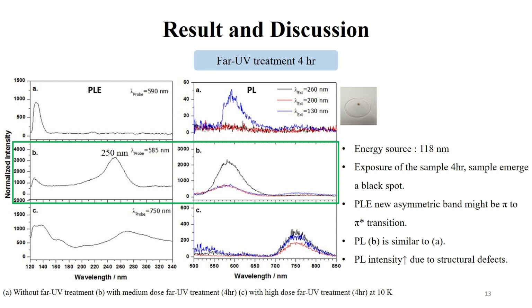Single layer graphene on magnesium fluoride with far UV treatment 4 hours. The energy source is 118 nanometer. After 4-hour treatment, the sample emerged a black spot like this. And PLE generate a new asymmetry band, might be pi-to-pi star transition. PL spectra of far UV treatment is similar to the A part, but the intensity increase might be due to the structure defects.